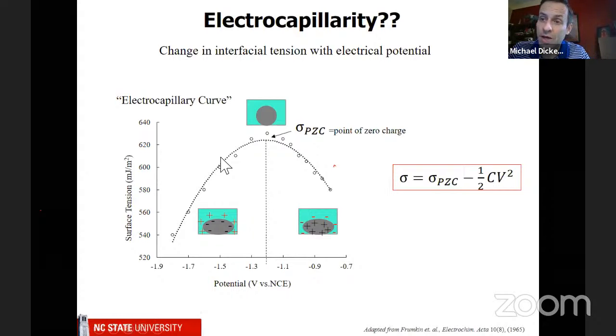Now, I want to make a couple of comments about this. Number one, if you look at this equation, you should get very excited, because what this means is if I apply a big enough voltage, I can make the surface tension be 0 or even negative. But you can see this is data from 1965. And in this data, they stopped measuring right here. The reason they stopped is because if you go too far in voltage, you actually get electrolysis of water. In other words, these charges start combining and you start getting reactions. So there's a limited window of voltage that you can do this.